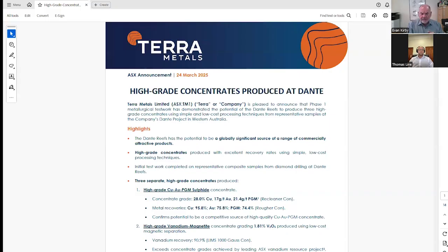We've conducted quite a brief test work program, 6 flotation tests on the Dante sample, 2 Davis tube wash. That's a low intensity magnetic separation on a very small sample, 30-gram sample, and then the magnetic separation or magnetic fractionation on a 2-kilogram sample of flotation tails. The results have been quite startling.